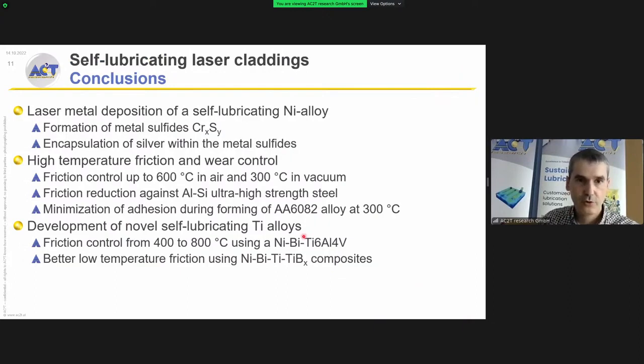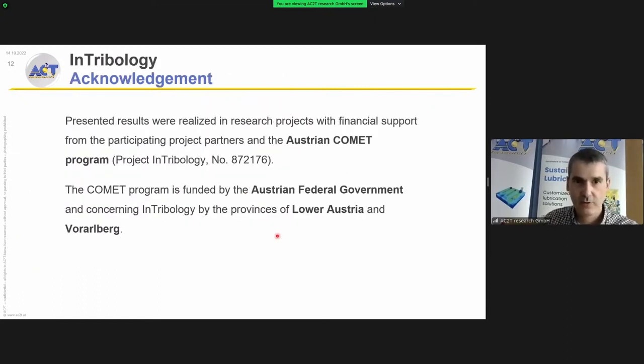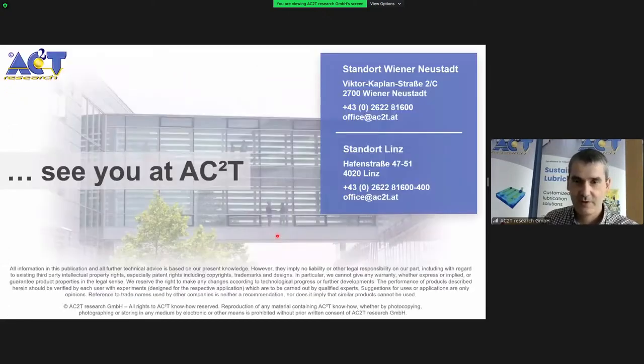So with this, I would like to conclude. I have shown you our initial self-lubricating nickel alloy that works by encapsulating silver in metal sulfide pockets, that it provides very good friction control in air until 600 degrees and 300 degrees in vacuum, friction reduction in different forming processes, and now our current work on self-lubricating titanium alloys. So with this, I would like to thank the Austrian COMET program for financial support, and also thank you very much for your attention.